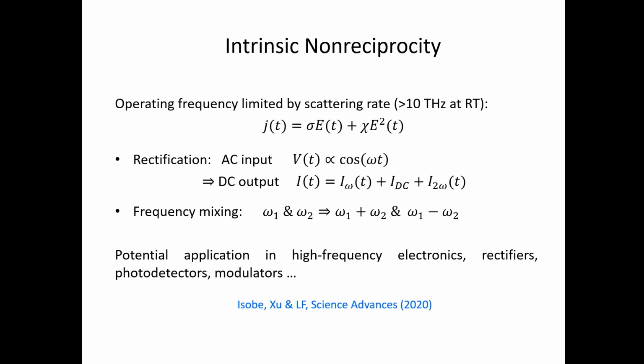Before I tell you the answer, let me also mention that if I have an intrinsic non-reciprocity of a homogeneous quantum material without invoking any junctions, then this IV relation can in principle work at a very high frequency that's basically only limited by the scattering rate of the material itself, which is typically on the order of tens of terahertz. It's in the infrared frequency range.